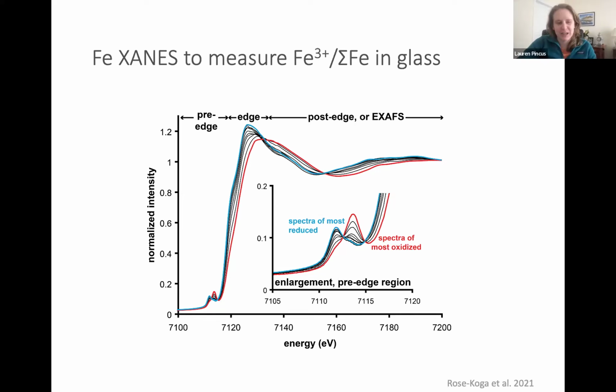And then the second question. That was the K-alpha HERFD for iron. Oh, for the pre-edge. I might be able to speak to it more. I suspect that in the case of iron XANES, the fitting uncertainty and the resolution of the spectra is usually much smaller than the uncertainty on the calibration when converting it over to iron. So for the application I'm using it for, I'm not sure it would improve the precision that much, but whether or not you'd be able to extract more information from more of the x-axis fusion might be a question for Matt.